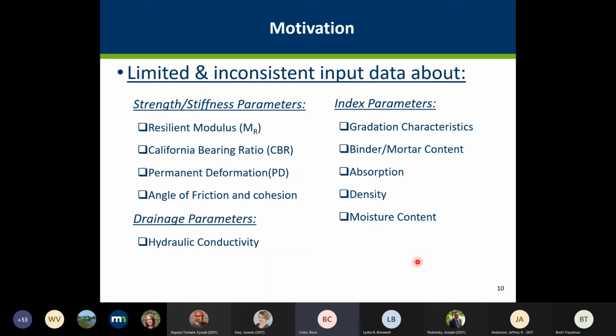I mean, there have been many studies conducted on these materials, index and engineering properties, but it was not collected in the sense of a database. So in the study, that's what we tried to do. We tried to collect resilient modulus, California bearing ratio, permanent deformation, friction angle and cohesion values for these materials, along with the other index parameters that we have here. Then also, in addition to collection of all this data, including hydraulic conductivity, we tried to correlate these index parameters to the engineering properties, either strength or stiffness parameters or hydraulic conductivity parameters, to see if we can give a range and then predict your resilient modulus values based on the gradation characteristics.